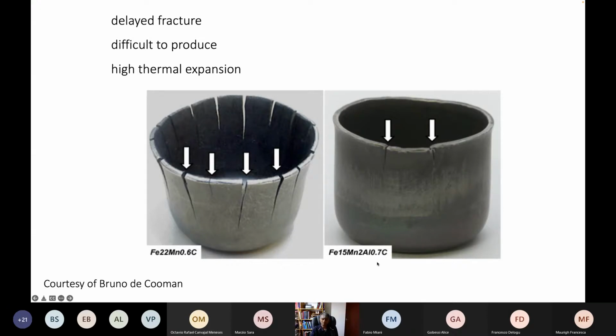But the addition of aluminium gets over the problem. However, when the delayed fracture problem was highlighted, the automotive industry basically abandoned TWIP steels because they thought of them as being unreliable. The problem is actually solved by the addition of aluminium. And there are various ideas on how this stops this mechanism of fracture, which is associated with hydrogen embrittlement. This kind of fracture can be accelerated by introducing further hydrogen into the material. So there must be something about aluminium which prevents that hydrogen embrittlement of austenite.